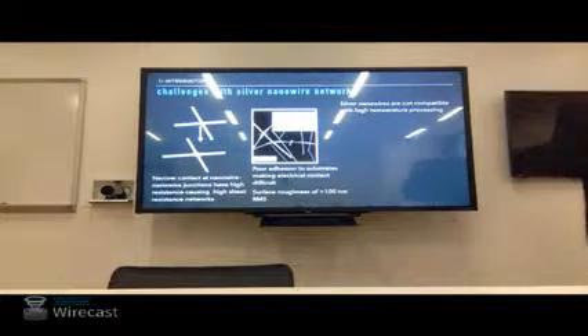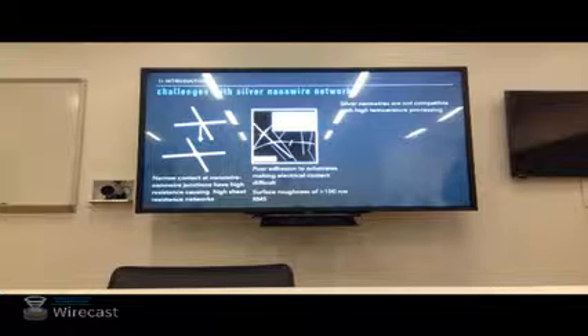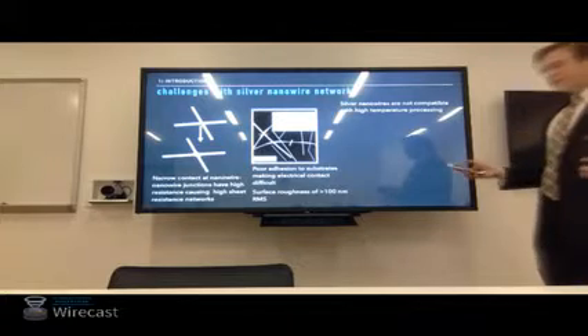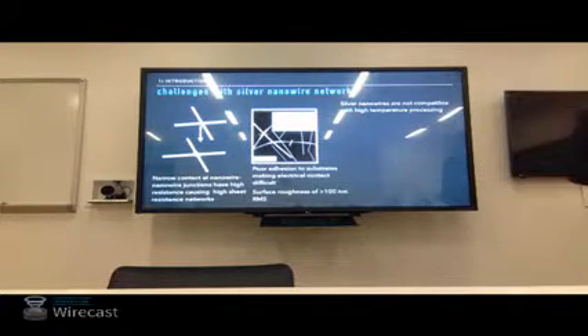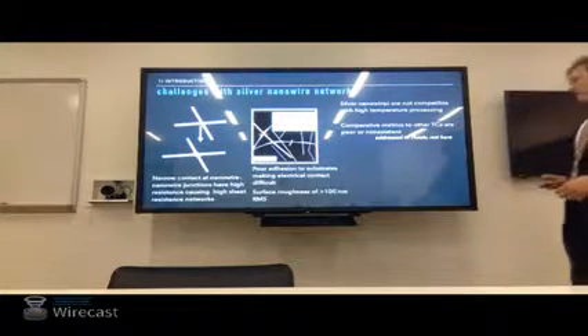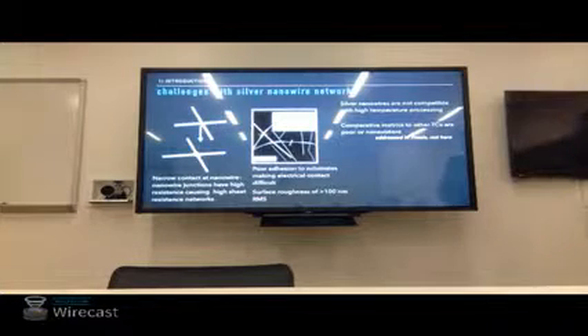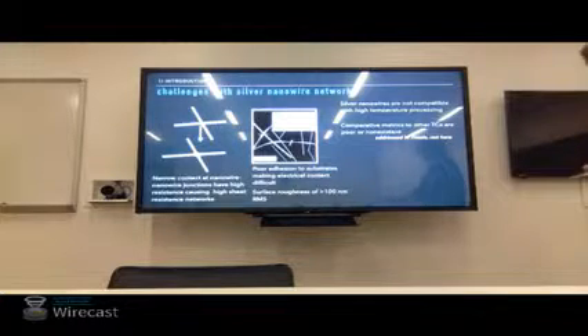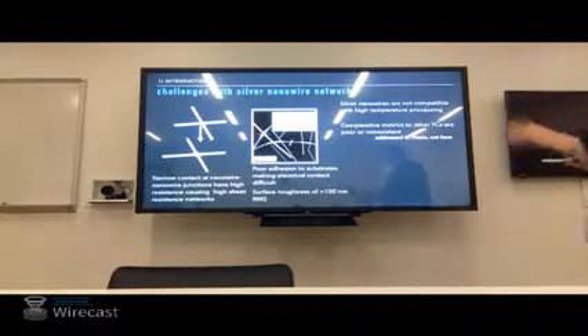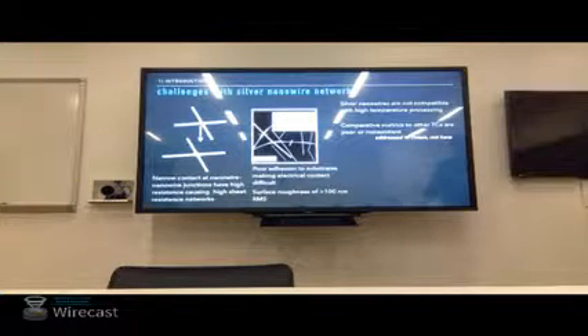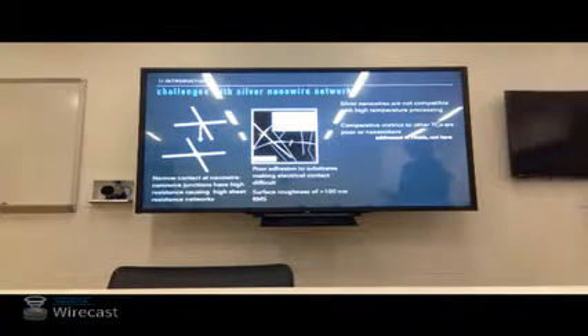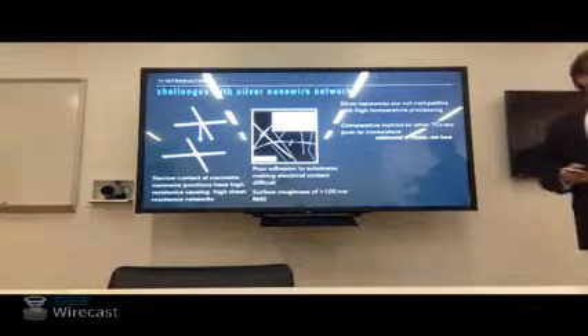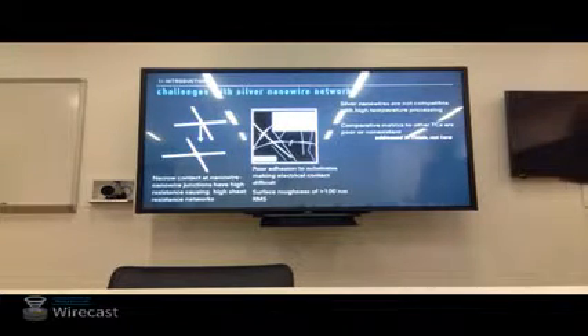There's also the issue that nanowires don't play well with high temperatures. Because of the nanoscale geometry, the melting point is far depressed from the bulk. You could think of it as the surface area to volume ratio. It's much, much higher in a nanowire than it is in a bar of silver. There also are not good comparative metrics of transparent conductors. It's not as easy just to say that I have a sheet of ITO and I have our silver nanowire network, they have the same sheet resistance and transparency, they're going to work the same. This is an issue that's addressed in the thesis, which is going around. We're not going to really cover it in the FPO today.